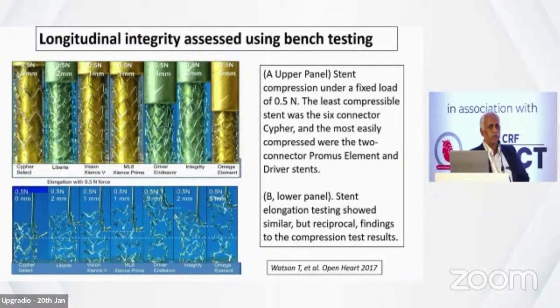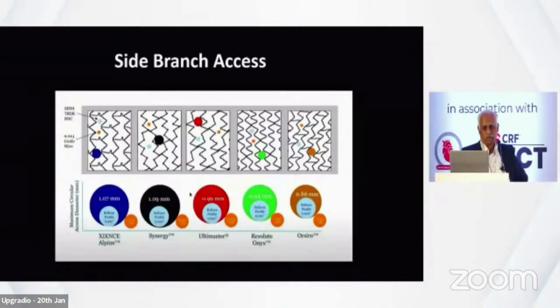Similarly, you have done a post dilatation, or you are exchanging a wire, or you are removing a balloon after the dilatation. If the longitudinal strength of the stent is not strong, it may get deformed while pulling. In the upper panel, the push pressure, and here they put a hook and saw how much pressure is needed to deform the stent. So depending on the pressure that you use, either pushing or pulling, you can distort the stent, and that will lead to problems. So we should know about the longitudinal stent deformity.